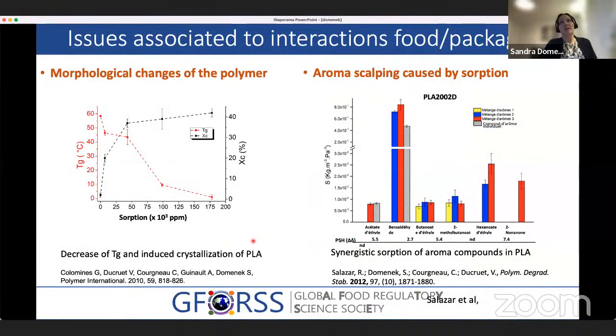Where the issues are is when we have strong interactions between the food and the packaging, which, for example, bring about morphological changes of the polymer. I give you an example here on PLA, which is getting plasticized by ethyl acetate. So you see the glass transition temperature of the PLA and the quantity of ethyl acetate sorbed inside the polymer, and there is a quite important decrease of this glass transition. And also an increase of the crystallinity of the polymer.